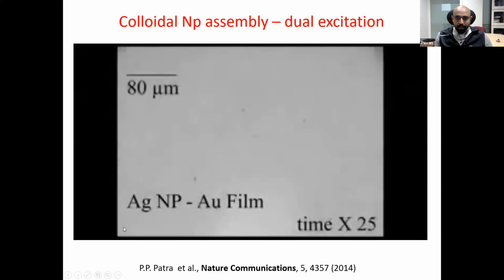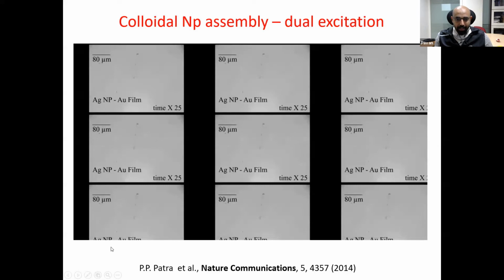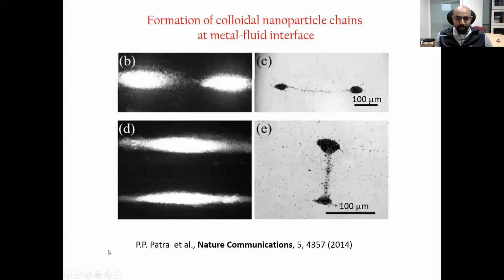For example, shown here is the excitation at two different regions. In this particular region, the assembly is forming, and there's another formation in another region. What is important is you also see an assembly which is formed between the excitation points. So shown here is a very interesting observation of nanoparticle chains purely because of an optothermal field. You have this excitation at these two points, but what connects these two nanoparticle assemblies is also a very interesting chain of nanoparticles. Okay, and there is no optical excitation here. It is purely due to an optothermal field, and this thermal field can really create a large chain of nanoparticles all at the metal fluid interface.